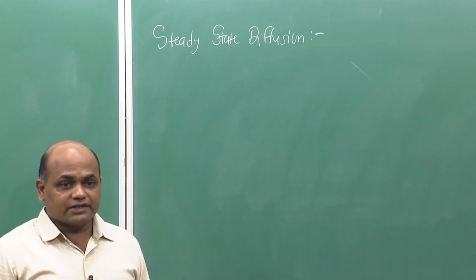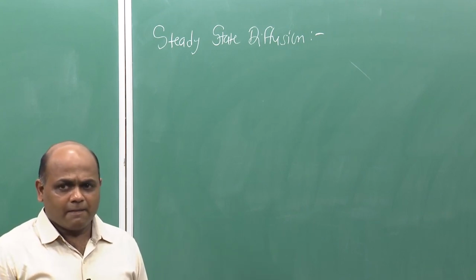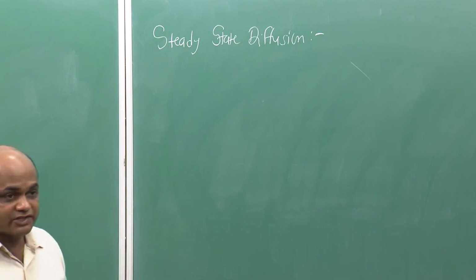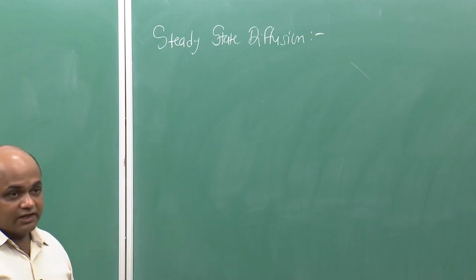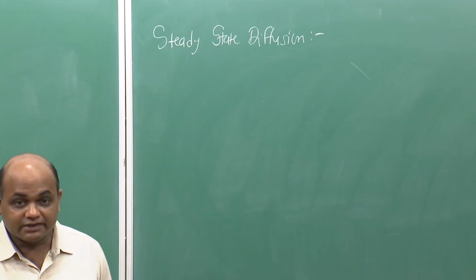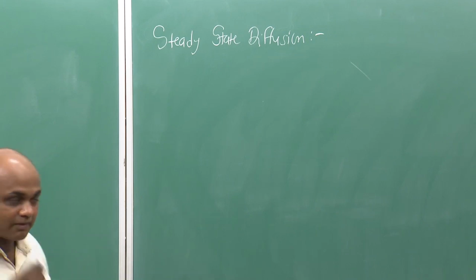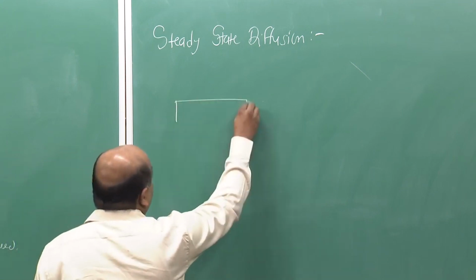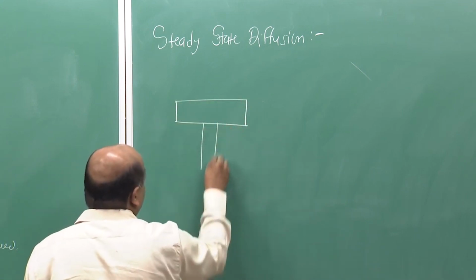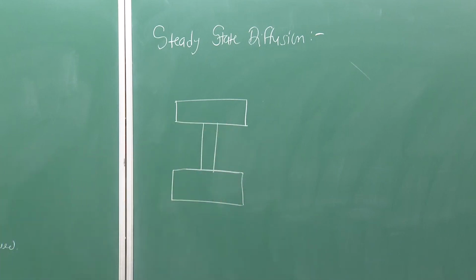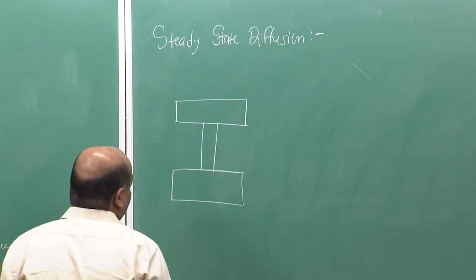So, what is a steady state? Right. So, the diffusion is occurring, but it is not causing any change in concentration at any given position. Okay. And the classic example is the experiment done by Fick. Remember what he did? He studied the diffusion of salt in water, and he developed a steady state for that. I explained this in the previous class, right.